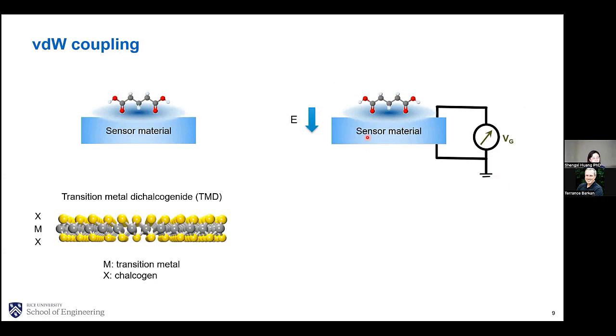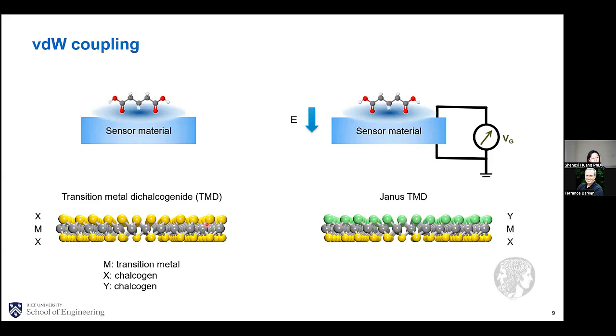Well, if we look at the fundamental atomic structure of a TMD, we can see from the side view, there is a layer of transition metal atoms sandwiched between two identical layers of chalcogen atoms like this. So what I want to do now is to replace an entire layer of these chalcogen atoms with another layer of chalcogen atoms like this. So by doing this, I'm introducing an out-of-plane mirror asymmetry and an intrinsic vertical dipole because of the difference between these two types of chalcogen atoms. So by doing this, I can introduce a vertical dipole.